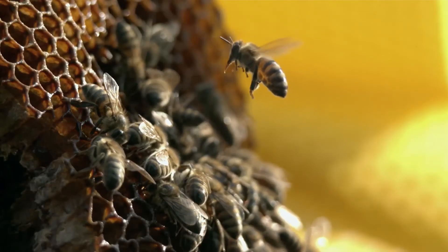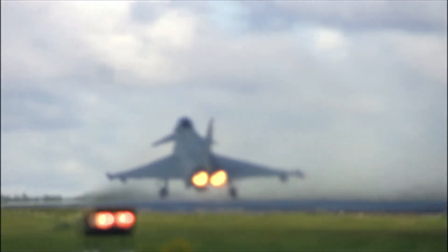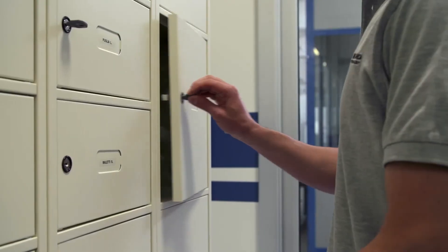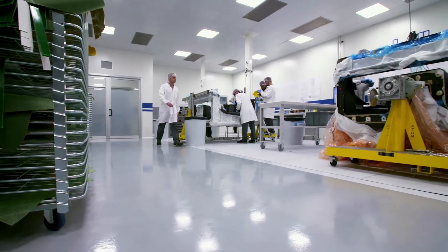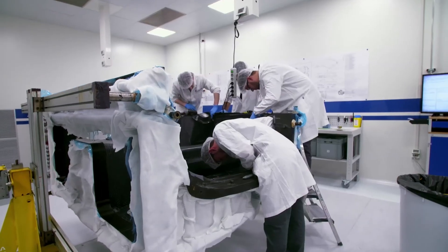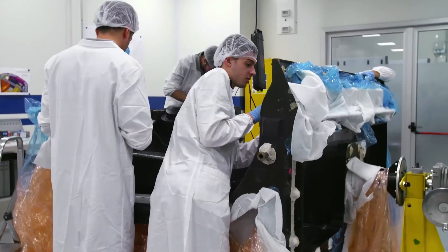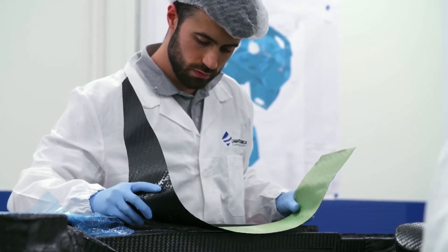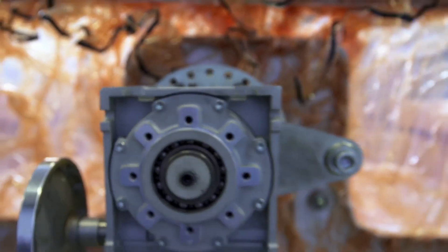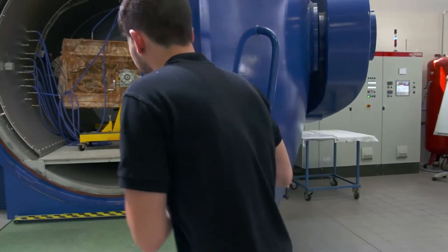The architecture that the team uses is similar to honeycomb: one skin of carbon, honeycomb, and then another skin of carbon. This is called a sandwich structure, typically from aerospace. Inside an aerospace-grade cleanroom, 50 artisans handcraft the honeycomb structure, where it takes 150 layers and over 1,500 hours to assemble a single monocoque. The process begins by layering carbon fiber sheets in a mold, before curing the unit inside an autoclave that bakes the monocoque at 135 degrees Celsius for over 15 hours.